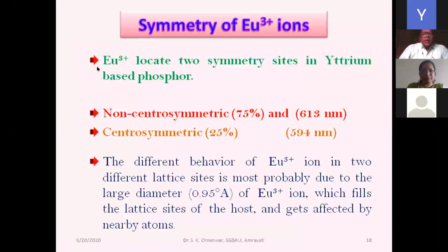The Eu3+ usually locates at two symmetry sites in yttrium-based phosphors. One is the non-centrosymmetric site, that is 75%, and therefore we get the 613 nm emission. And when it is located at the centrosymmetric site, 25%, then we can go for this, responsible for J equal to 1, this is responsible for J equal to 2, that is 594 nm.